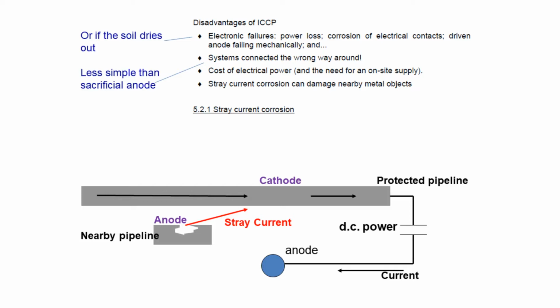This kind of stray current corrosion is a major problem which can be caused by powered corrosion protection systems doing cathodic protection. If the local environment, say the ground in which these pipes are buried, is a busy environment, and this is often the case in cities or industrial plants, precisely the places where you use ICCP systems, these are the places where there is actually a risk of there being other infrastructure in the ground which might be destroyed by an ICCP system.